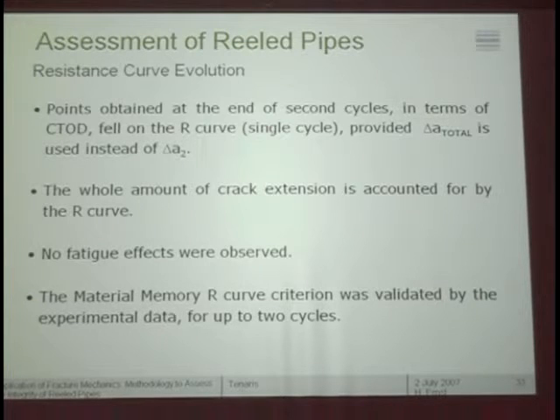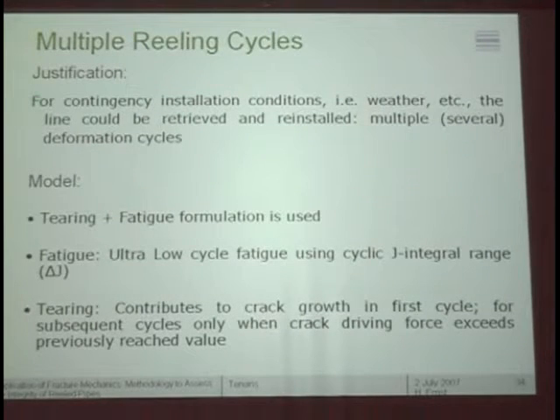Only two cycles, please remember that. No fatigue effects were observed. Again, only two cycles. Okay? Obviously, if we put more cycles, sooner or later the fatigue will come in. The material memory resistance curve criterion was validated by the experimental data for up to 2 cycles for this material.